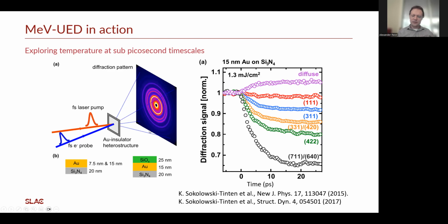As we record these diffraction patterns for different delays, what we see as a function of time, this is the graphic on the right here, is that the various reflections decay. I would just like to note that here, because this is a polycrystalline sample, instead of getting these very intense peaks, they've now become rings. This is simply because of all of the different orientations of the crystallites within this sample. But these, again, correspond to well-defined reflections in the crystal.